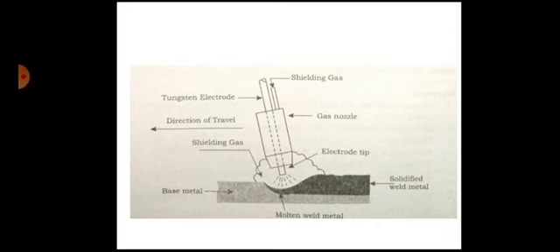Then the working. Welding current, gas and water supply are turned on. The arc is struck by touching the electrode with a scrap tungsten piece and then broken by increasing arc length. This procedure is repeated twice for warming up the electrode.